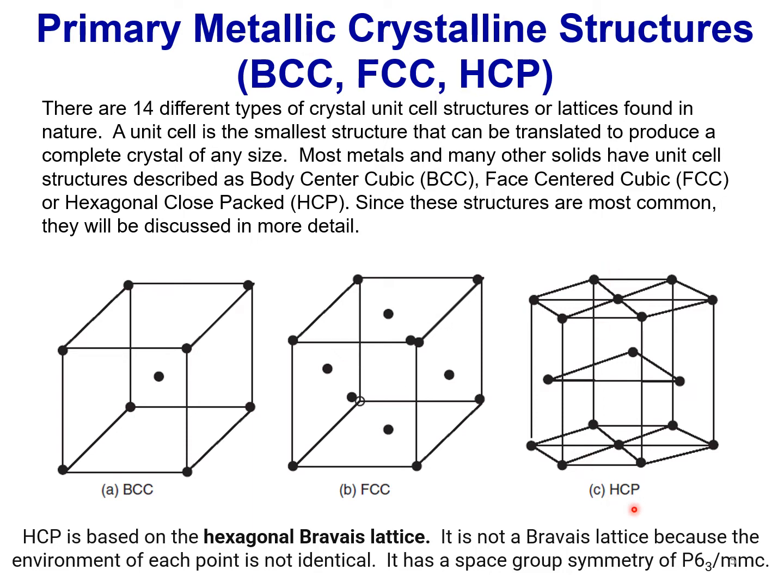Hexagonal close packed, of course, is the lifeblood of the CANDU industry, because CANDU reactors are made from zirconium alloys because they run on natural uranium, and zirconium is the best material to use, which has high strength, good corrosion properties, and has a low neutron absorption cross section.